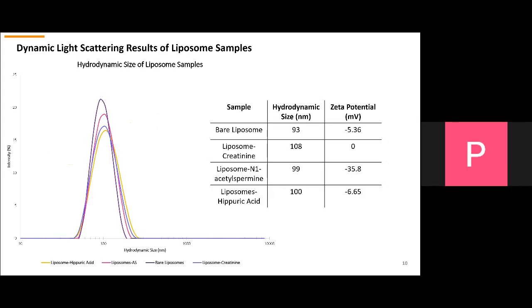Another technique to analyze our nanoparticle samples is dynamic light scattering. Here we're able to gather the relative hydrodynamic size as well as stability as indicated by the zeta potential. Our bare liposomes have a hydrodynamic size of 93 nanometers with this technique, and you can see this increases after post-insertion of the linker and the metabolite. As well, the more negative the zeta potential value, the more stable our sample is in solution and the less prone to aggregation it is.